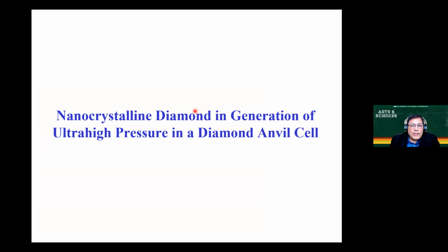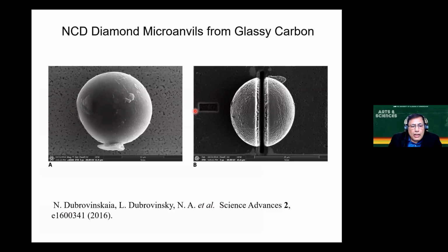So we were dormant for 2 decades. And there was a very interesting development then from the group of Natalia and Leonid Dubrovinsky on creating these diamond microanvils from glassy carbon. So they took these glassy carbons, subjected them to high pressure and high temperatures, and created this nanocrystalline diamond. And what caused the most excitement was that